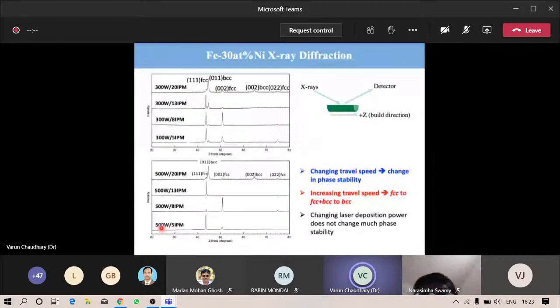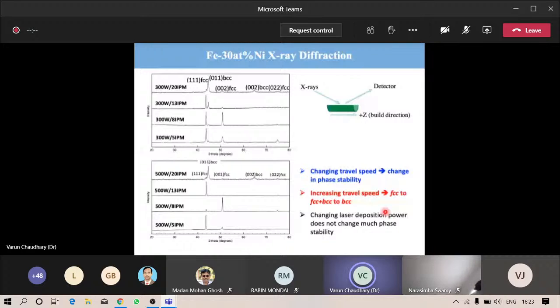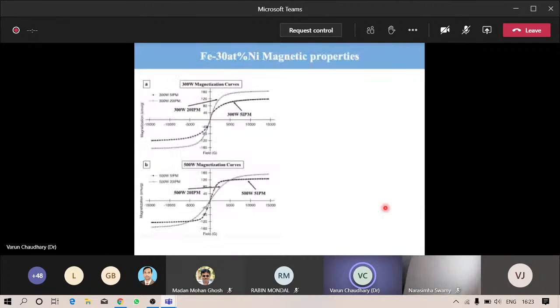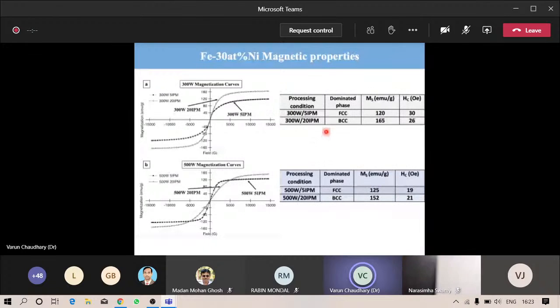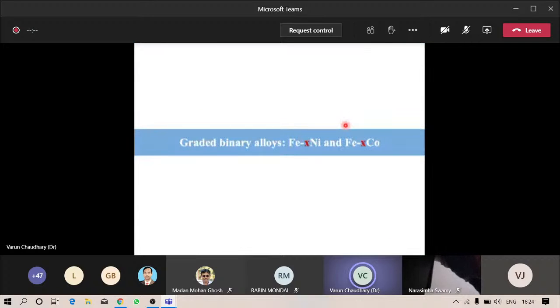Same in this other set of experiments, when we increase the power and change the speed. So we can increase the travel speed, and then we can convert the crystal structure from FCC to FCC plus BCC and then BCC. Here are the results for that. And yes, by changing the process parameters and therefore the crystal structure, we found a significant change in the magnetic properties: the face-centered cubic structure has lower saturation magnetization, and the body-centered cubic structure has higher saturation magnetization. So by tuning the process parameters, we can tune the magnetic properties. Let's move to the graded binary alloys, iron nickel and iron cobalt.